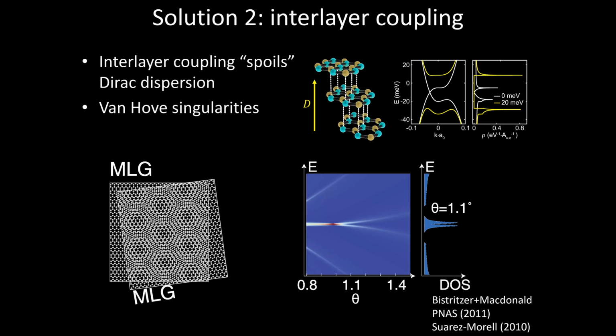What's important, though, about these moire systems is that they also introduce a superlattice. Okay, and that superlattice gives you something commensurate, and you can now think about band structure not only at the scale of the whole graphene Brillouin zone and the lattice of the graphene, which is angstrom scale, but rather now something that's more like 10 nanometer scale. This is important because if you want to get incompressible insulators in a solid state system, you need to be at some commensurate filling of the lattice. And commensurate filling of the lattice in a graphene crystal means zero charge density. But once you have the superlattice, you have a whole new superlattice band structure, and you can imagine insulators that happen even at finite carrier density relative to charge neutrality. That's going to be a very important thing.